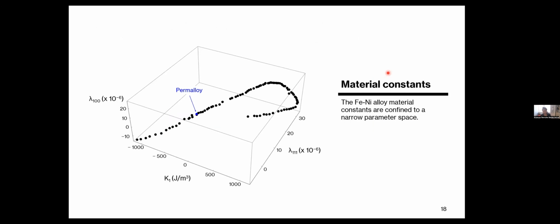And it makes us rethink when you think of the alloy development strategy. Here is a plot which shows the range of anisotropy and magnetostriction constants that was explored by Bozorth and Walker back in the 1950s. And it shows this one alloy, one specific composition which has a value quite close to zero and extremely small magnetostriction values. They're of the order of 10⁻⁶ microstrains. And this is one specific alloy that gives you the smallest coercivity and makes us rethink, are we not examining the wider material parameter space? Because there could be several of these magnets in the wider material parameter space for delicate combinations of these magnetostriction and anisotropy values, but somehow our alloy development strategy is focused on making kappa 1 close to zero. I'll be missing out on several combinations of these constants where there could be other soft magnets with non-zero anisotropy values, which could be developed, but we're just not looking for them.